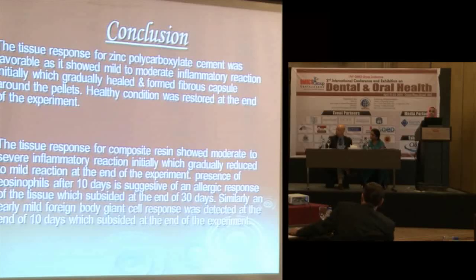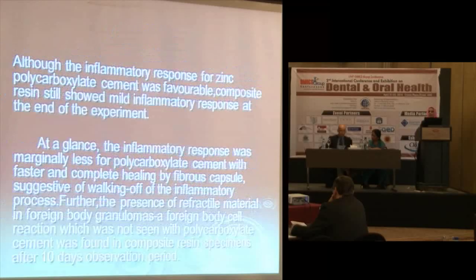The tissue response for composite resin showed a moderate to severe inflammatory reaction initially, which gradually reduced to mild at the end of the experiment. Presence of eosinophils after 10 days is suggestive of an allergic response of the tissue, which subsided at the end of 30 days. Similarly, an early mild foreign body giant cell response was detected at the end of 10 days, which subsided at the end of the experiment.